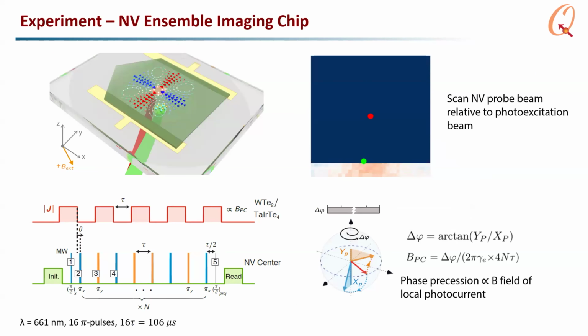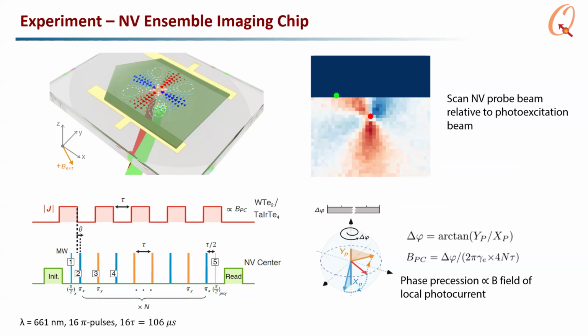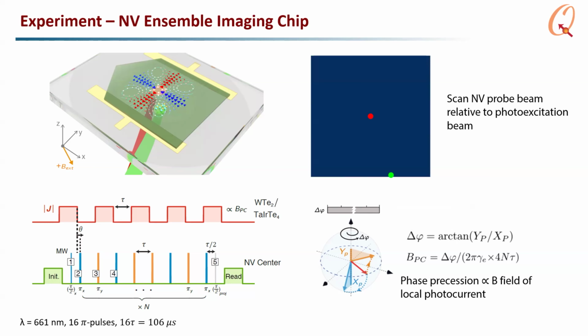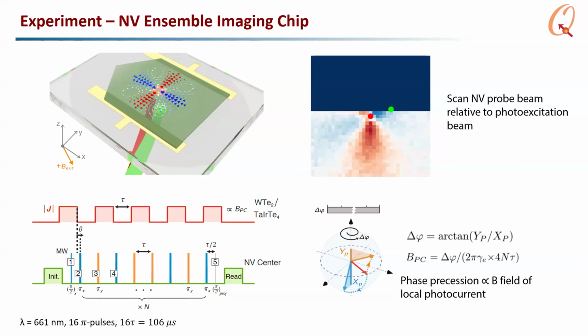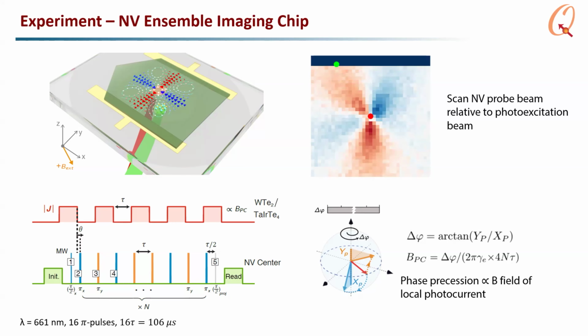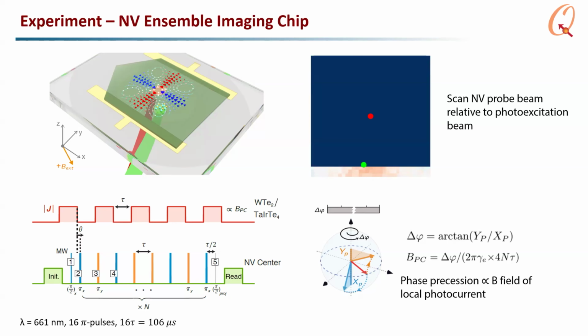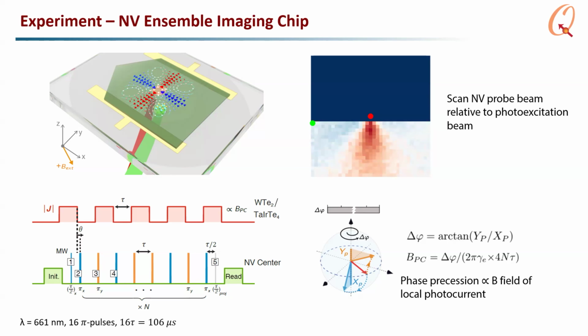So we tried to look at the flow of these photocurrents with NV center magnetometry. Here we have an ensemble imaging chip where there's NV centers everywhere. The diamond membrane is very thin, and our light comes in from below. We shine light through the diamond membrane onto the WTe2 sample to excite photocurrents, and then we raster the NV center readout beam relative to the photo excitation. Then we can map the stray field relative to the photo excitation, where the phase precession is directly proportional to the stray field of the photocurrent, and then we can apply the current reconstruction